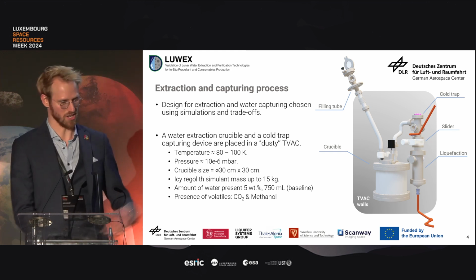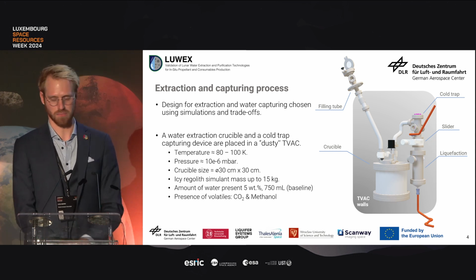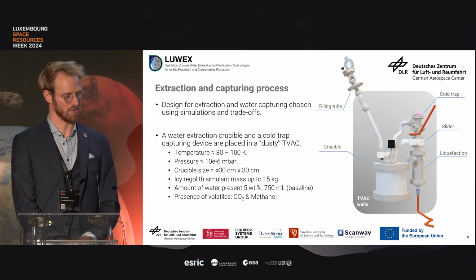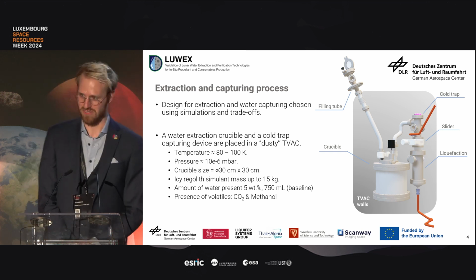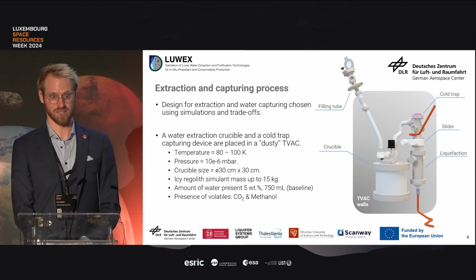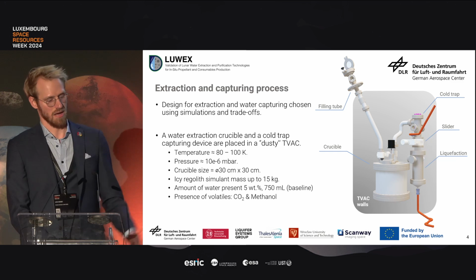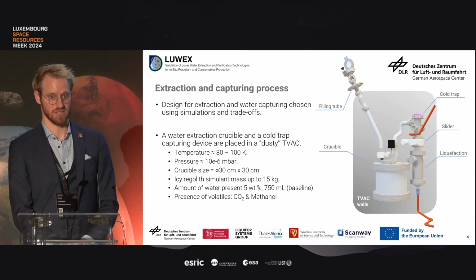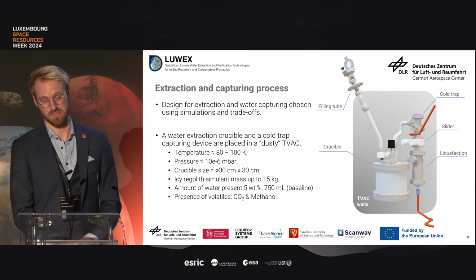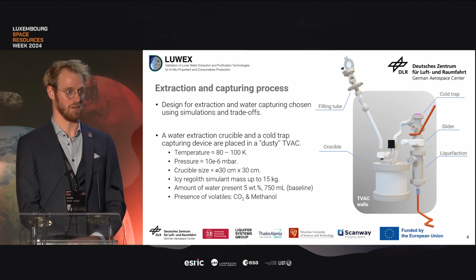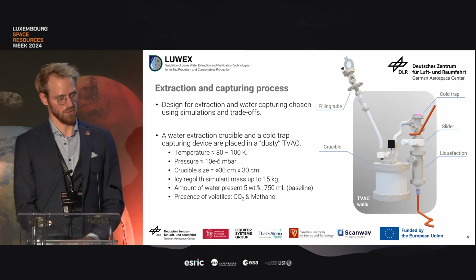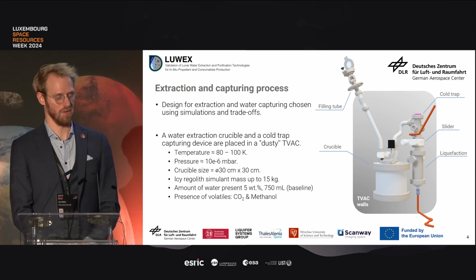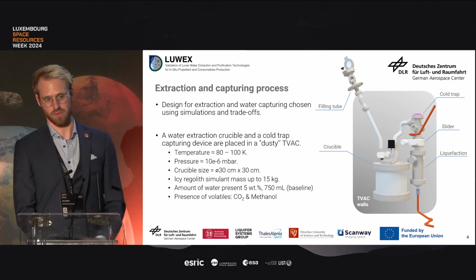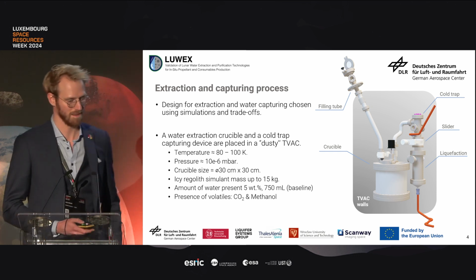And just to give you an idea of the size of our system, the crucible there at the bottom has a diameter of 30 centimeters and a height of 30 centimeters. So that is more than enough volume for our icy regolith sample. And we want to go up to 15 kilograms of icy regolith. For example, if we had a 5% weight percentage there, that would mean 750 milliliters of water that we could potentially extract. We also want to add other volatiles like CO2 and methanol in the ratios that they were detected by LCROSS. So let's have a closer look at our crucible.